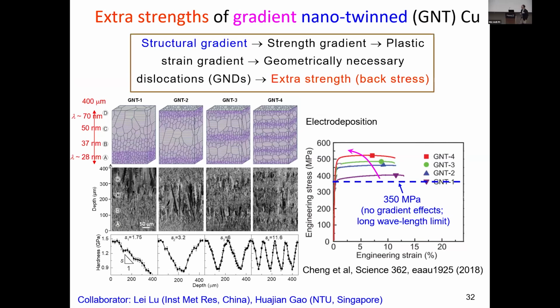Next, I'll introduce a more in-depth study to quantitatively understand this internal stress effect. One question is, since we have very strong internal stresses, can we further push the limit so that we can get an extra strengthening effect that's beyond the rule of mixture, right? So you have hard and soft phases, but the result is not just following the so-called rule of mixture. In this particular case, we use electrodeposition to fabricate this so-called gradient nanotwinned copper microstructure.